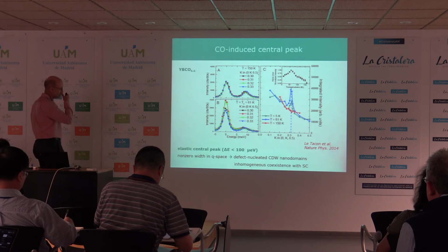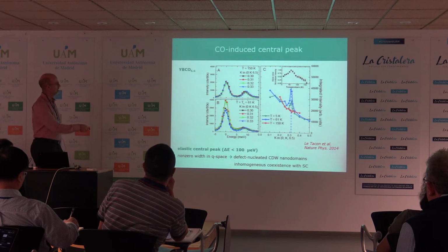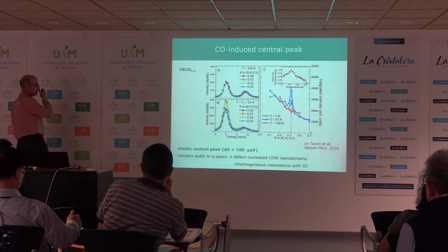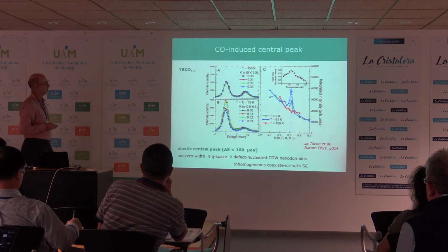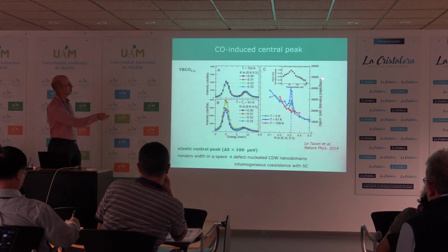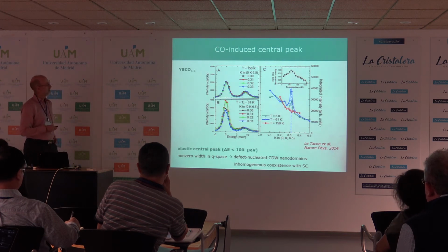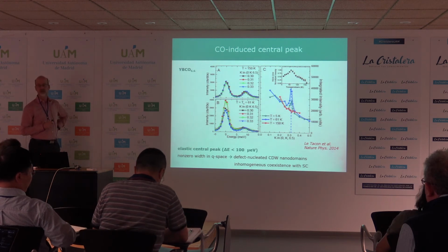We also then look at the same kind of data. So these are phonons here we were studying. We also see here at zero energy an anomaly at the charge density wave vector. Okay, so this is now looking at the temperature dependence, but in an energy resolved way. And you find that this charge density wave peak is actually perfectly sharp in energy.